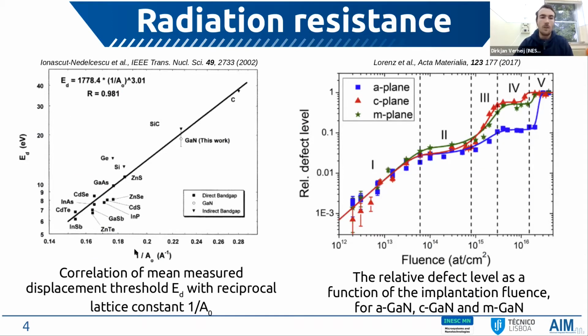So if we take a look at this graph on the left, which shows the displacement energy thresholds as a function of the reciprocal lattice constants of several materials. And for those who do not know, the displacement energy is basically the energy necessary to remove an atom from its original position in the crystal lattice. And basically, the higher this energy, the more difficult it is to displace the respective atom, and consequently, the higher the resistance of the material to radiation. And as we can see here, gallium nitride is located all the way up here. If we compare it with, for example, other typical semiconductors used for radiation detectors such as germanium, silicon, or even gallium arsenide, the value for gallium nitride is much higher.